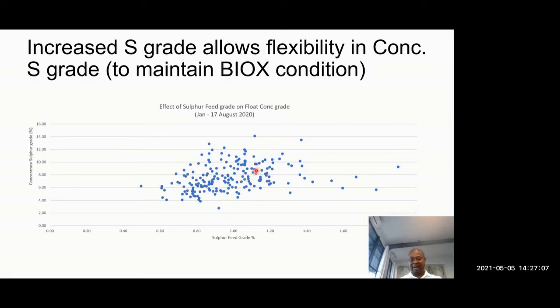But why is it exciting? Well, it's exciting because of the method we are using to do the oxidation. The BIOX: if you put too much mass, you pull too much gangue with it, and therefore the sulfur percentage goes down. But at the same time, it's a catch-22. If you don't pull enough, you don't get your recovery of gold in the first place. Here we are not processing the flotation tails. We throw them away. So you need to get as much of your gold in the flotation concentrate as possible, but at the same time, it has to be high enough grade for the BIOX to be happy, the bacteria to be happy.